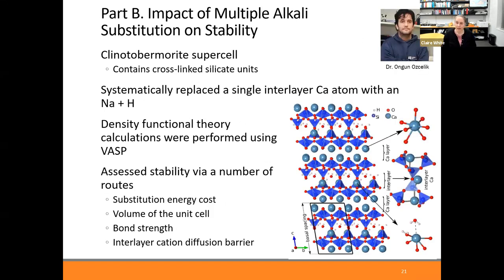Once again, we did this from a computational viewpoint, and specifically here we used a different structure. I'm not going to go into the details, but it's called clinotobermorite. There were reasons why we looked at this structure. What we did, in the interlayer region of this structure, is systematically replace single calcium atoms with sodium and look at the energy of the system with replacement of, say, one and then two and three and four and so on. Once again, we did these calculations using VASP, and once again, we could analyze various properties of the structures that came out of the calculations.